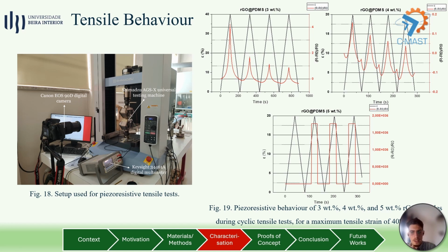With the bending tests over, we took the best performing samples and tensile tested them using the setup of figure 18, and these showed us that the material structure and the conductive network conformation had a lot of influence, with a pronounced leakage between the first and second cycles, as well as lower strain and sensitivity values. Here, the 3% sample reached a gauge factor of 4.89, followed by the 4% sample at 0.43, and lastly, the 5% sample, where due to its extremely exacerbated response, the gauge factor could not be calculated.